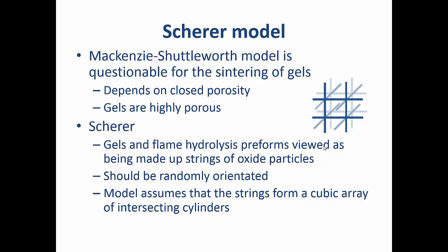One reason those earlier stages have tended to be looked at is that with viscous glass sintering, people have been interested in the sintering of gels to produce sol gel products. And in fact, the Mackenzie-Shuttleworth model is very questionable under those circumstances because it depends on closed porosity,